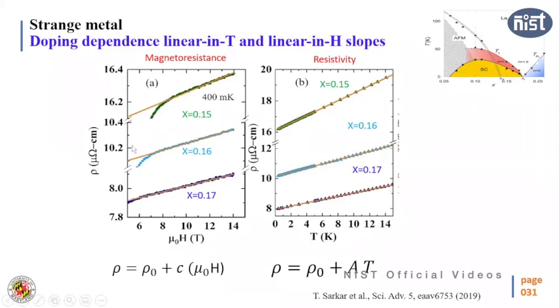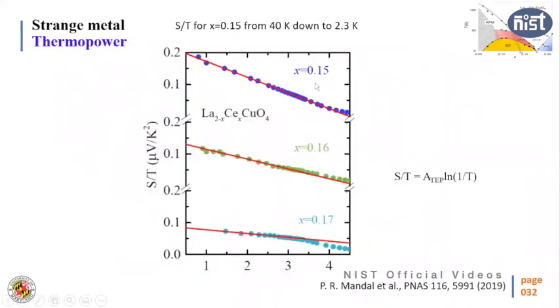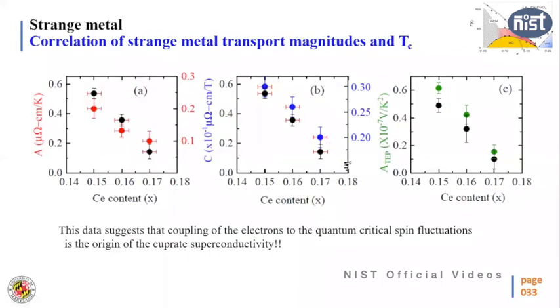Same thing could be done for the magnetoresistance. We can fit all this data using similar linear equation, and one can calculate the value of C. And also for the thermopower, if we fit this S by T with this logarithmic 1 by T behavior, we can calculate the value of A_TP. What we found, if you take all these values, this A we got from the resistivity as a function of temperature, and the C from the magnetoresistance, this constant value, and also the A_TP,